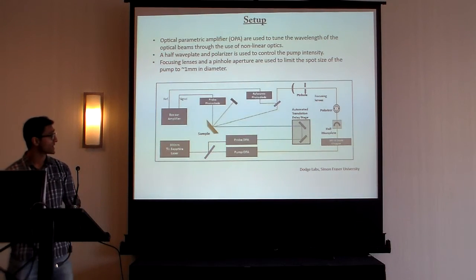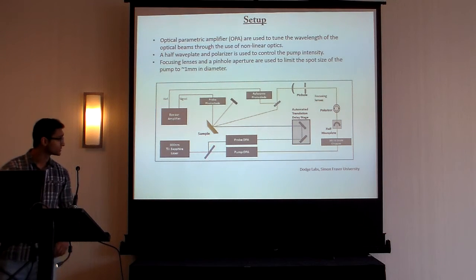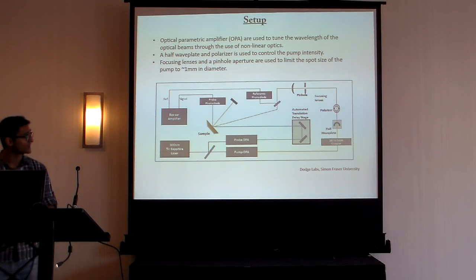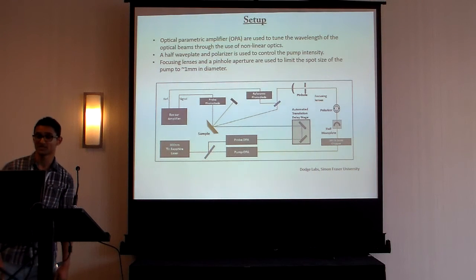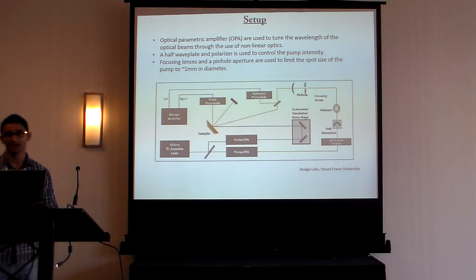So here's a schematic of our experiment setup. At the bottom, we start off with two optical parametric amplifiers, which use frequency doubling techniques and nonlinear optics to convert this 800 nanometer titanium sapphire pulse laser into a wide range of output frequencies. Following the pump OPA, with a repetition rate of 1 kilohertz, it goes through a 500 hertz beam chopper, which takes out exactly half of the pulses. And these missing pulses are used as a reference signal.